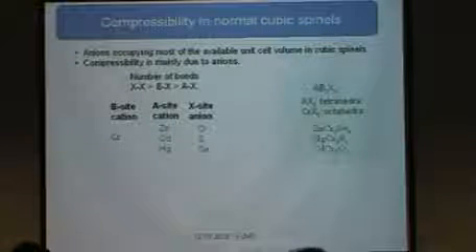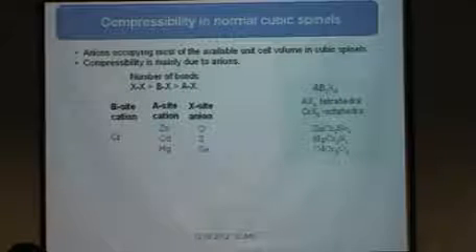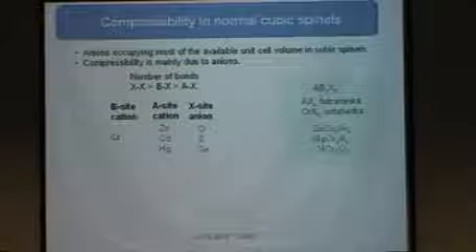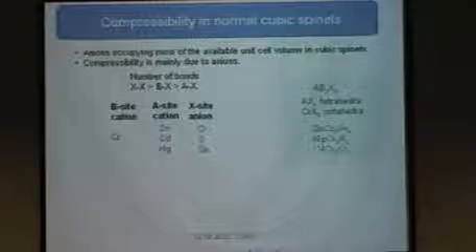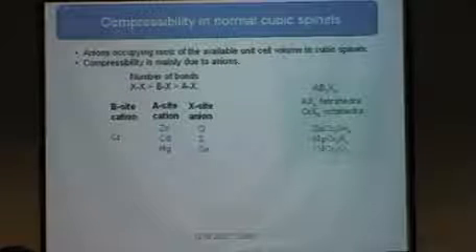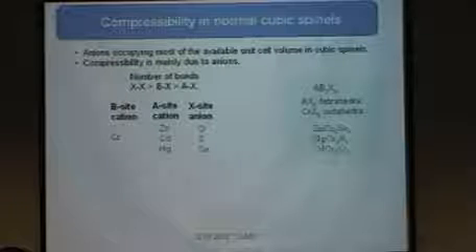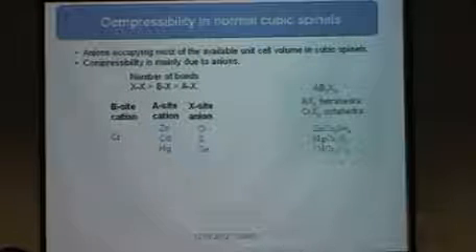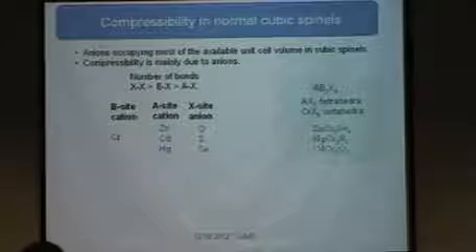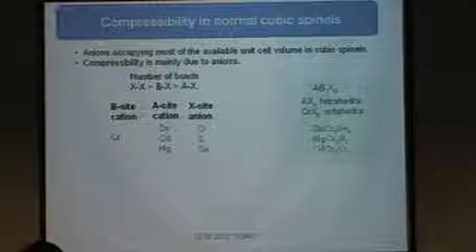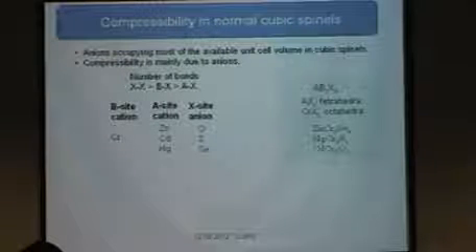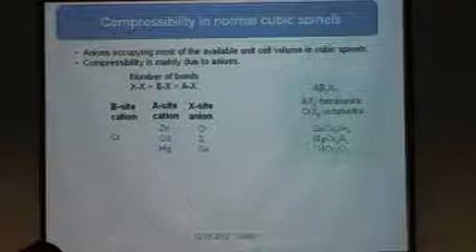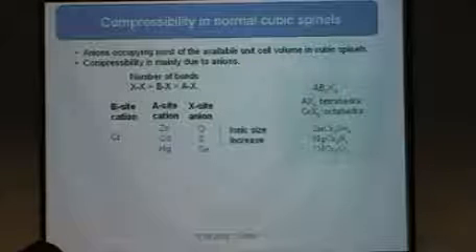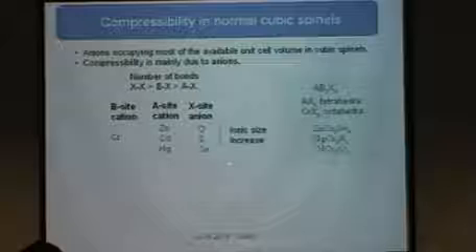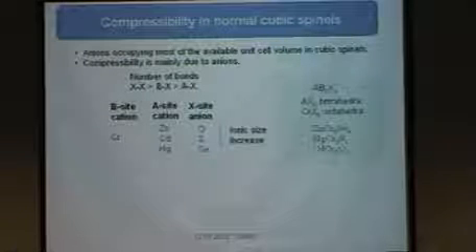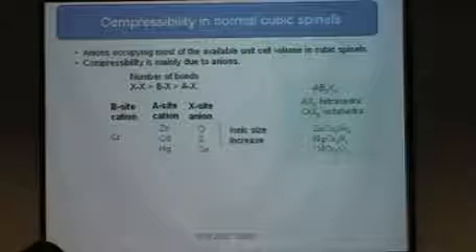Since for this studied compound the A site was different, and besides this the X site is also different, it's not easy to compare all these three compounds. So what I can do is, if you see that the volume of the cubic spinel's anions is more compared to the other cations, one can say that compressibility was mainly due to anions, because the number of bonds between anions is more compared to the others, as I mentioned before. And what's an anion? That's oxygen, sulfur, selenium. And going from top to bottom, ionic size increases.